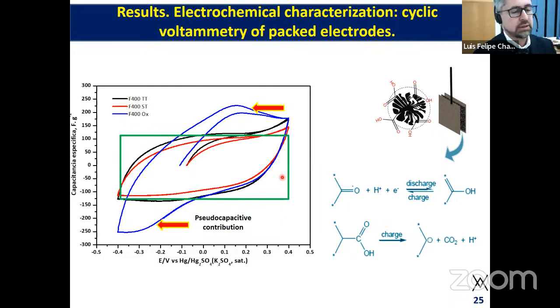Here in this slide, we also noted that these materials exhibited a nearly rectangular voltammetric response, which is the typical response of an electrochemical capacitor, where the response of the most oxidized material, which is the blue line, also presented a contribution of secondary Faradaic reactions that may not favor the electrosorption process. What we want is more capacitive materials, like the red and the black line here.